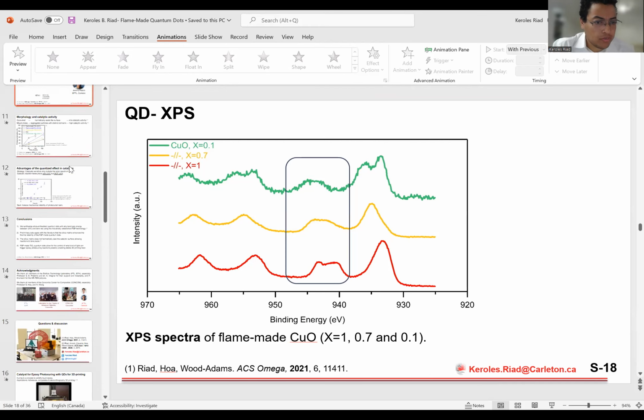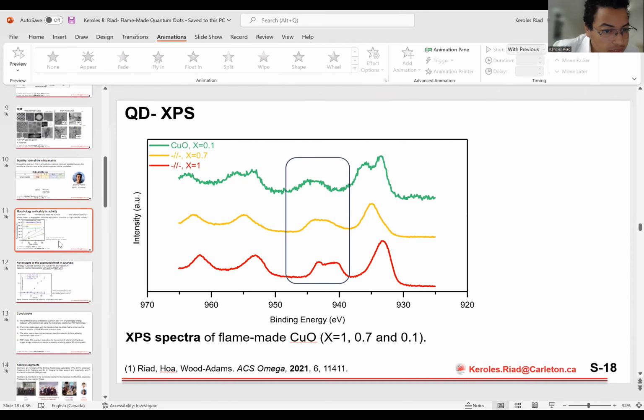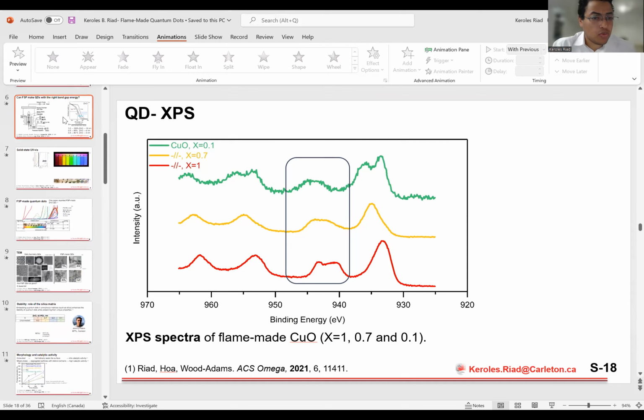Part of Tilika's work, where she compared the core shell structure to the mixed phase structure, was that the core shell was made using a ring on top of the flame, where the silica is added after the core material is built. So this is how the core shell structure is made. With mixed phases, the precursors are mixed at the same time, so the metal oxide is within the matrix without being coated. And this is really important because the surface has to still be available for catalytic reaction. With catalysis or gas sensing, the surface still needs to be available, and so you cannot hermetically seal it. That's really critical.